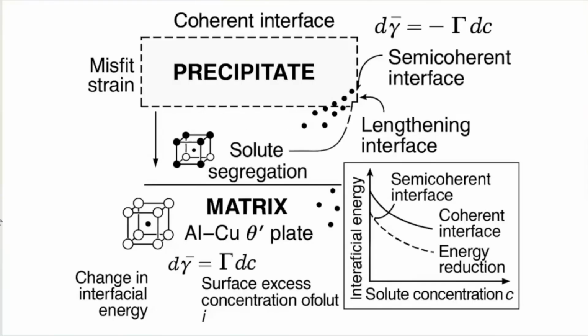At the time we started work, there was work again in Seidman and Dunand's group where they have shown that copper can segregate at the interface. Basically, this is a precipitate of theta double prime, theta prime, and at the growth interface, this is semi-coherent and the broad face is coherent. Immediately you can see that there's a change in interfacial energy as a function of composition, depending upon the nature of the coherency. Interfacial energy decreases with solute concentration for an incoherent, semi-coherent interface far greater than a coherent interface, mainly because segregation is larger in those interfaces.